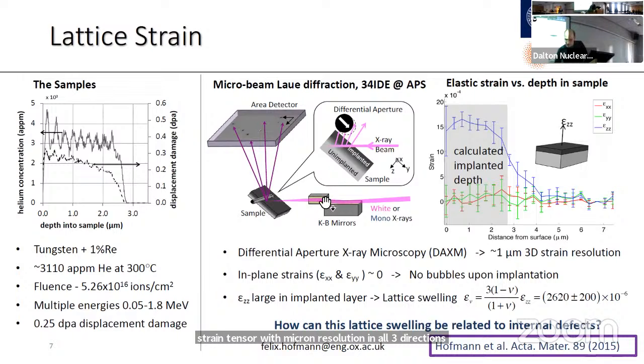So you have your X-ray beam that comes in here, like this, and then your diffraction pattern would have contributions from all the bits of material along the beam that your X-rays see, right? So in order to deconvolve what comes from what depth, you scan a wire through these diffracted beams, and by subtracting the images from subsequent Y positions, it's effectively as if you were moving a slit across your diffracted signal, and you can then reconstruct what the strain at different depths is.